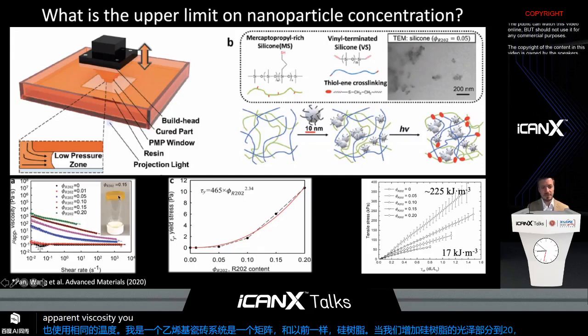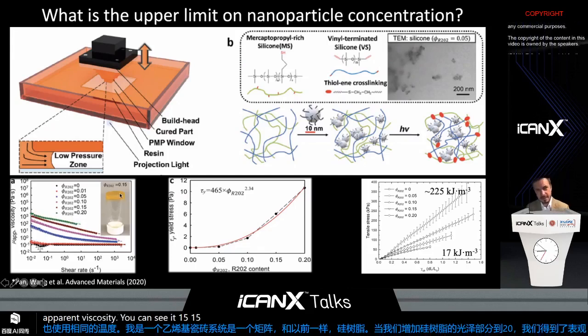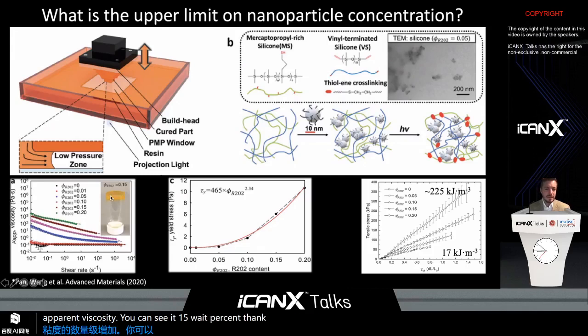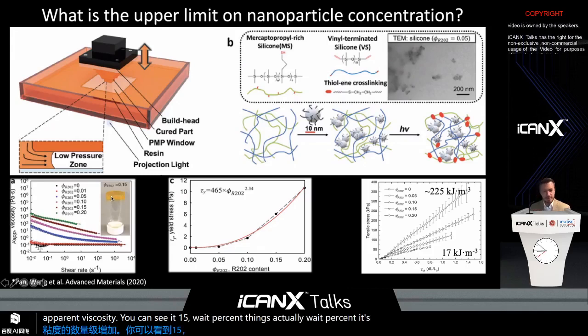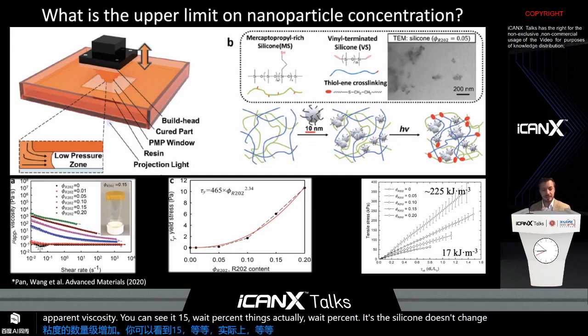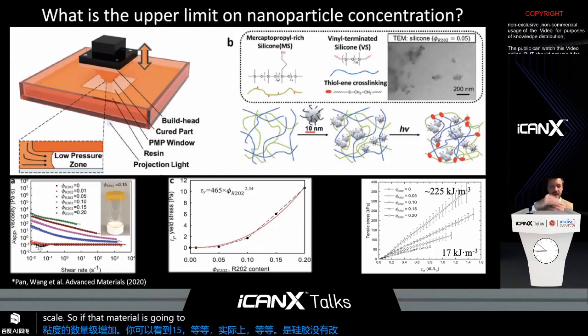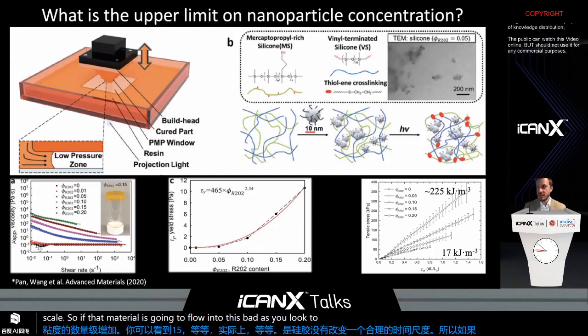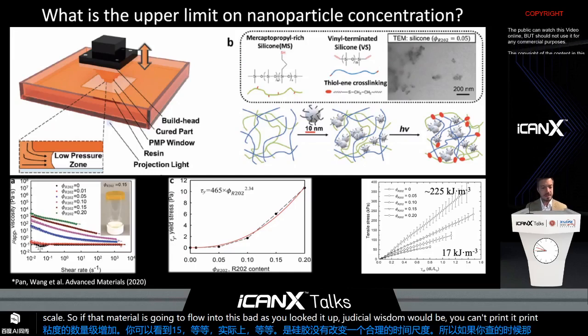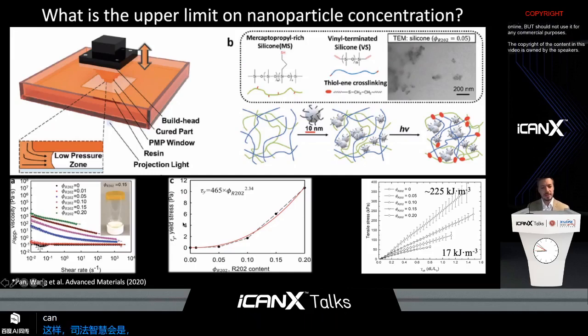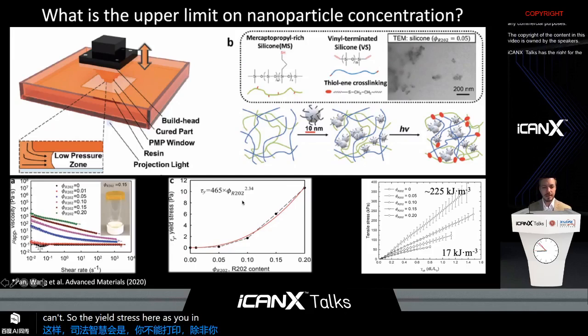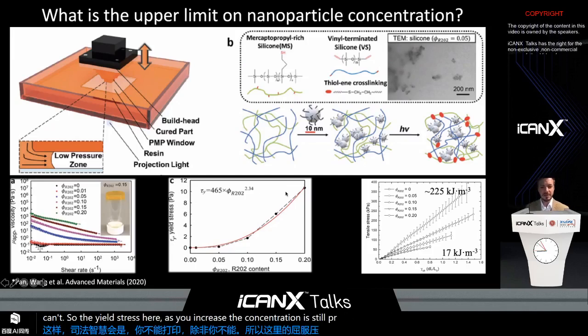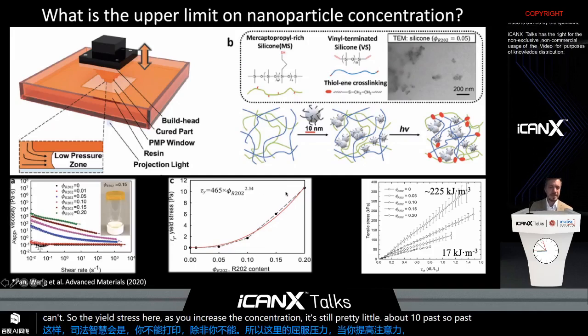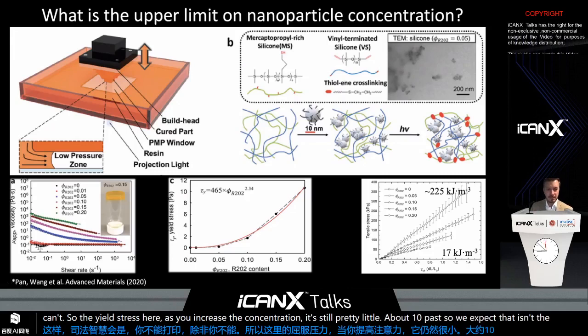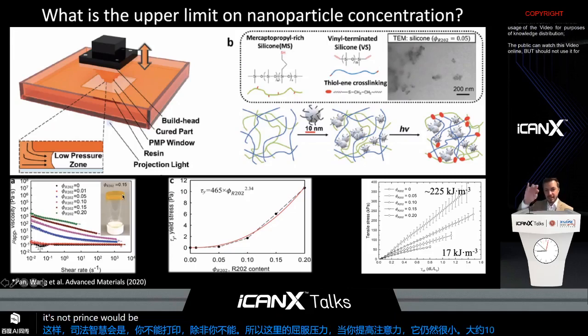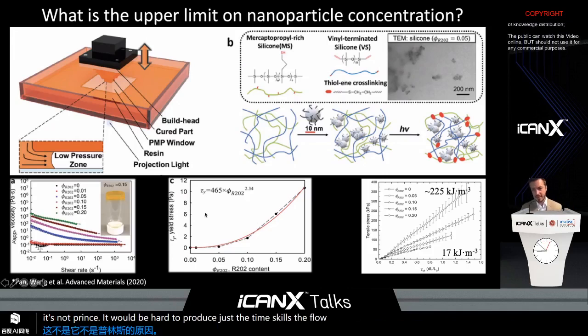And you can see at 15 weight percent, I think it's actually weight percent, the silicone doesn't flow down at a reasonable time scale. So if that material isn't going to flow into this vat as you lift it up, traditional wisdom would be you can't print it, except that you can. So the yield stress here, as you increase the concentration, is still pretty low, about 10 pascals. So we expect that isn't the reason it would be hard to print. It's just that the time scales of the flow are so incredibly high with these high viscosities.